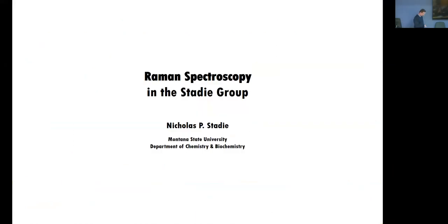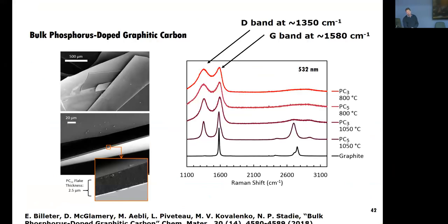Nick Stadie's group out of chemistry and biochemistry, they are working on phosphorus doped graphitic carbon. And they have worked with our scope quite a bit. And basically they're characterizing their phosphate doped graphitic carbon, again, through Raman spectra. What Nick tells me is that this peak out here is very indicative of graphite, and you can see the standard here. While these peaks are the D and G band, where the G band tells you something about the electric conductivity of the material. And again, these are important for fuel cells, electrochemistry, and so on and so forth.